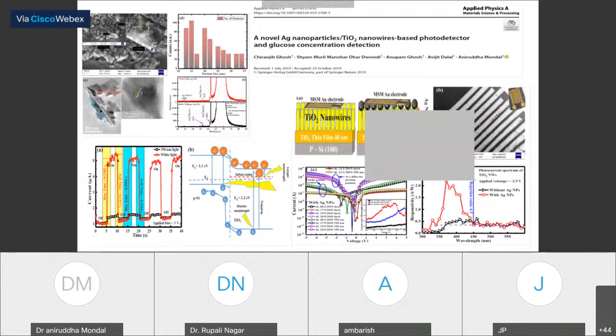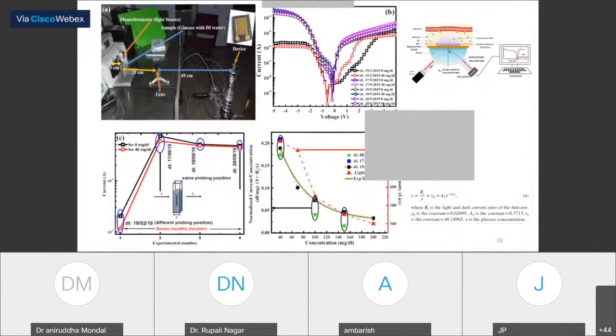So for the biosensor, we have used this photodetector as a biosensor. We have used two different kinds of structures. First, we have used the titanium dioxide nanowire based MSM photodetector, and second we have used the plasmonic based MSM photodetector. Figure B shows here the top view of the electrodes that we have used. We have characterized this photodetector for different wavelengths, and we have seen this photodetector is more responsive in the UV region, and we tried to measure glucose by using this photodetector.